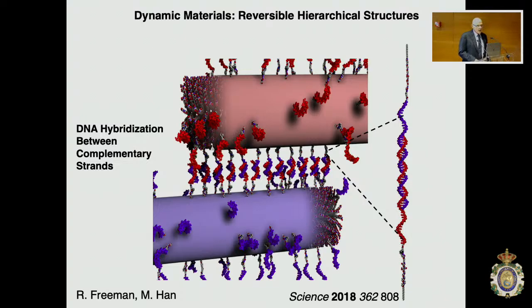How did we discover that? Well, you look at 2 filaments here, blue and red, and on the surface, we put DNA. We put a single-stranded DNA sequence, and the red one and the blue one are complementary, which means they do the Watson-Crick pairing that happens in our genes, in the nuclei of our cells, where the nucleotides recognize each other. Well, this is the same phenomenon. They're complementary. And the reason we did it is because we wanted to find supramolecular ways of joining the filaments to create perhaps more complex structures.